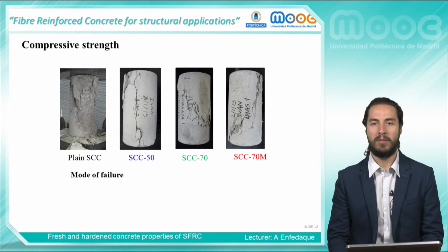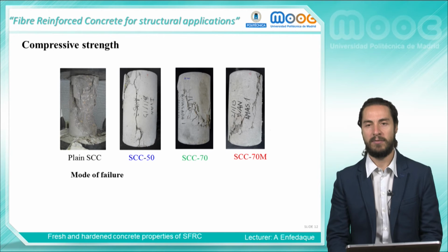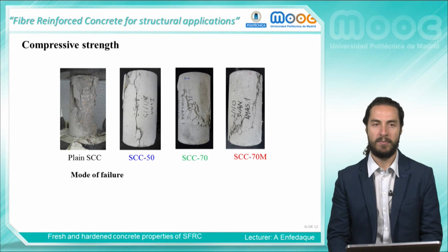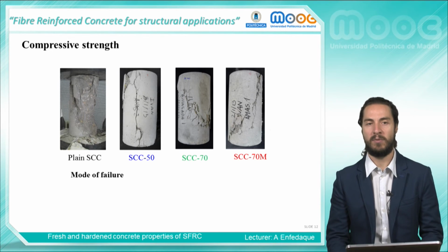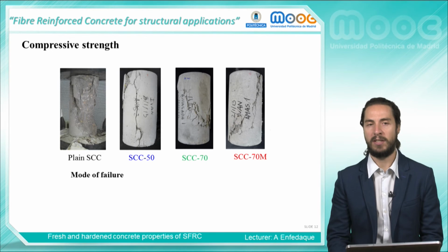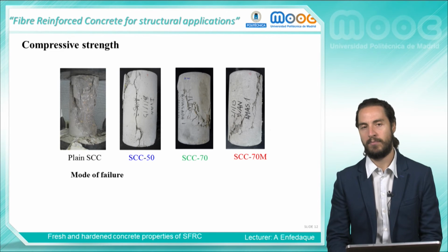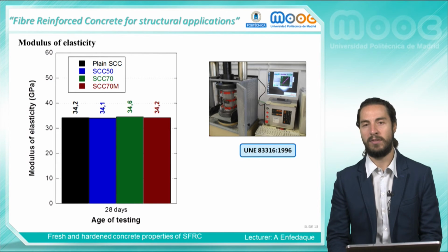However, the mode of failure is completely different from that of plain concrete. The plain concrete specimens fail with the typical brittle fracture and a broad mode, while the specimens with fiber show a very smooth fracture without any mass loss. With regard to the values of elasticity modulus, the results show no clear trend, and only minor differences were obtained.